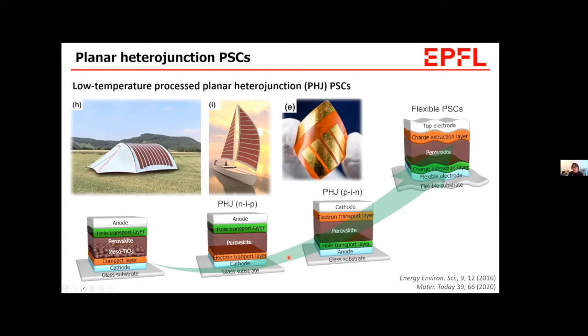Many electronic devices are being developed toward the flexible configuration for future electronics, but the mesoscopic perovskite solar cells cannot be made flexible because the mesoscopic structure should be sintered at high temperature, over like 400, 450, 500 degrees C, which makes flexible substrates deformed, not available. Therefore, to establish flexible perovskite solar cells, this kind of planar heterojunction perovskite solar cells, which do not use this high temperature processed mesoscopic structure, can be a practical option because it can be processed at a low temperature.